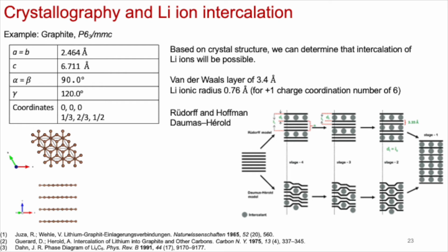Okay. So this is all to say, if you understand the crystal structure, then a model like this can arise, and the fast ion diffusion will be in the layer, in the basal plane, as opposed to in between, right? Because even between these two models with the staging, you could see that it's going to be more difficult to have diffusion in the C-axis than in the A-axis, but that's because of what the crystal structure of graphite looks like. Which extends to the argument of lithium cobalt oxide and similarly ion diffusion in R-bar-3M lithium cobalt oxide.